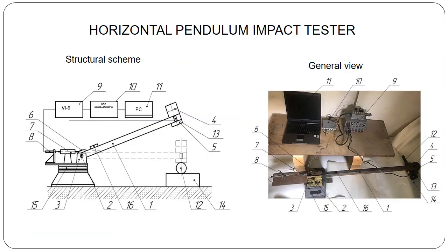A physical picture of the destruction of the material by a single impact, and the main dynamic characteristics of the crusher were determined on the developed laboratory installation with a horizontal pendulum impact tester. The installation includes a pendulum, at the free end of which there is a shock assembly. The fastening of the impactor allows you to set a different profile of the working surface that interacts with the glass. The height of lifting and dropping of the impactor is determined by the measuring system.